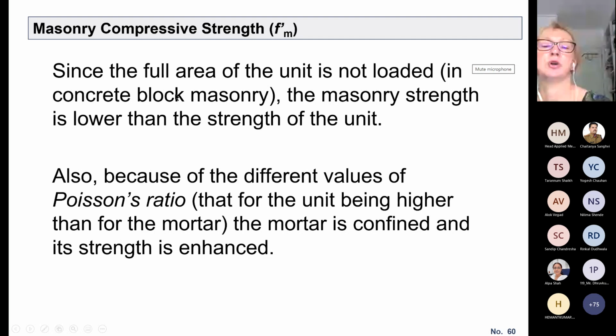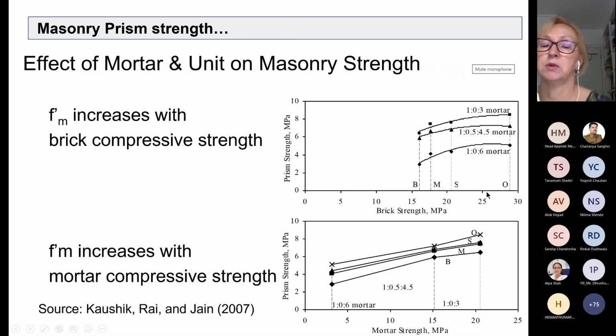The reason the strength of masonry is lower than the strength of the unit is that there are different values of Poisson's ratio, that Poisson's ratio for the unit is higher than for the mortar. So the mortar is confined and its strength is enhanced, but those differences in Poisson's ratio are making a difference between the strength of masonry and the strength of the masonry unit. So here are some results again from the work by Kaushik, Rai, and Jain. You can see that they tested actually 4 brick strengths. One type of brick strength was 16 megapascals. B bricks, M bricks are maybe 18, S bricks are about 20, and then O type bricks are close to 30 MPa. So these O-type bricks are very high for India. So you can see here the influence of prism strength depending on the mortar type.